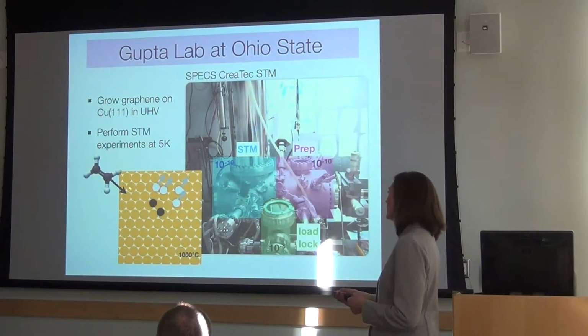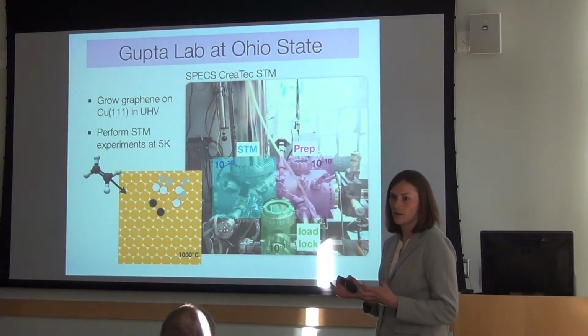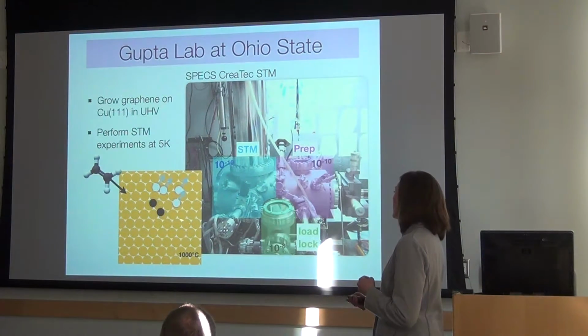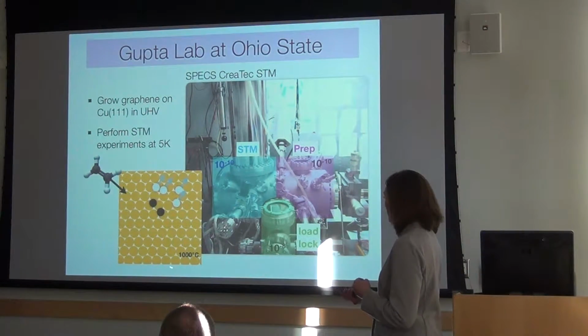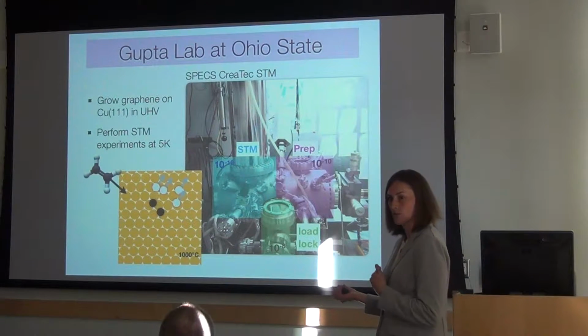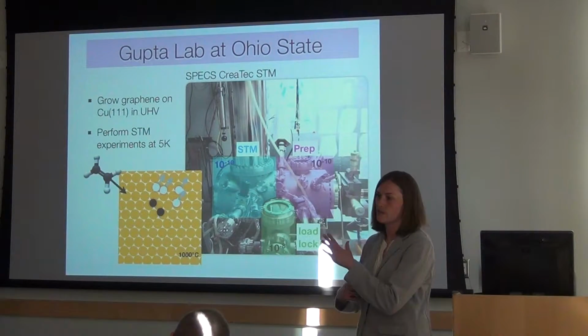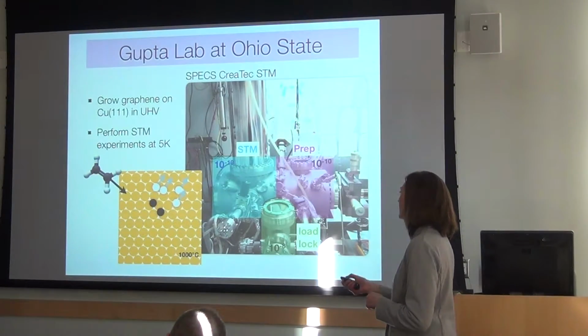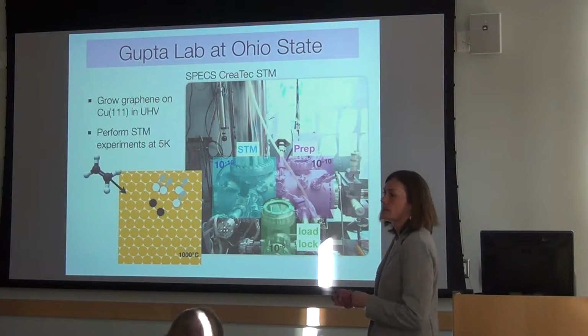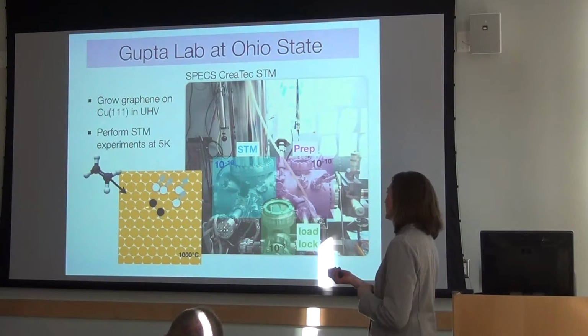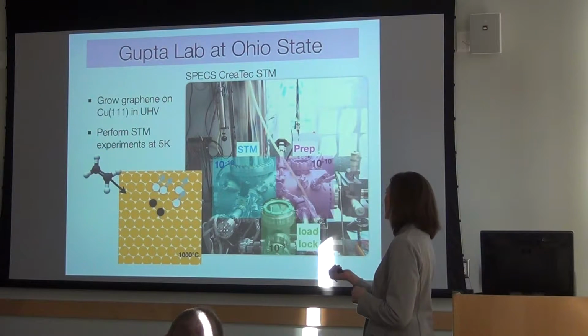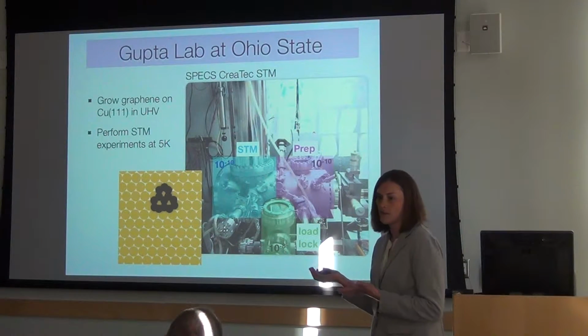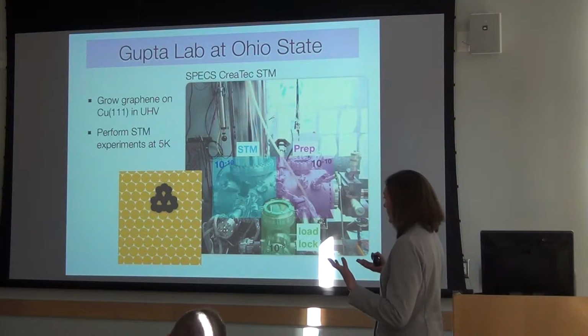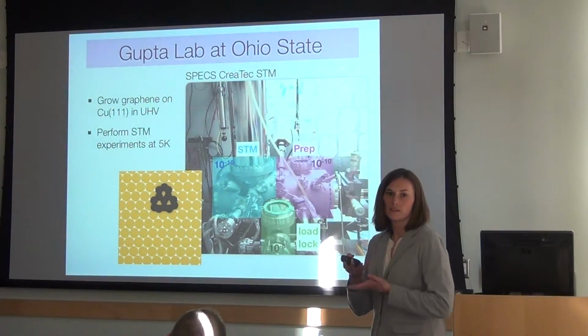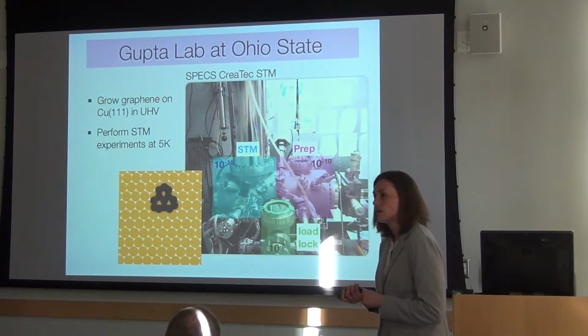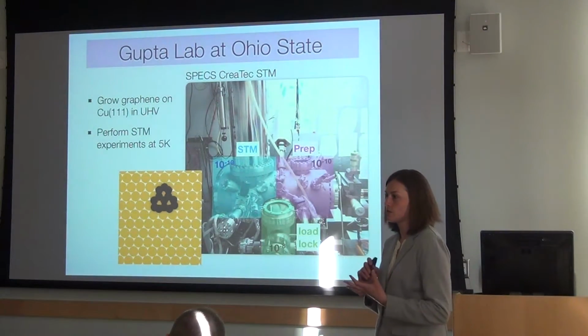in order to do this in high vacuum conditions. So what we do is we leak in ethylene at 10 to the minus 5 millibar, very low pressure of ethylene, and we cycle the temperature of the copper substrate. This is the 111 face of the copper crystal. And we cycle the temperature up to close to the melting point of the copper, around 1,000 degrees Celsius. And this helps dissociate the ethylene on the surface. The carbons stick behind, the hydrogens flip away, and we repeat this process until we have enough carbon dissolved on the surface, and then we cool down the crystal. The carbon actually surface segregates to form this hexagonal network. So that's how we grow graphene islands on copper in ultra-high vacuum.